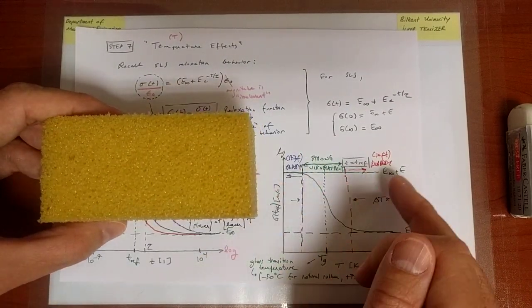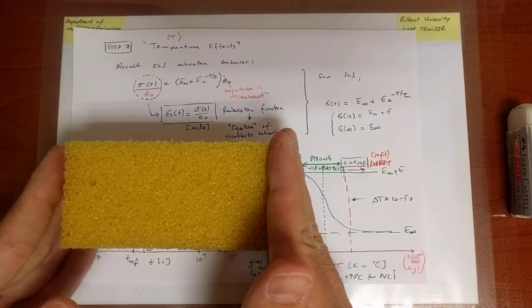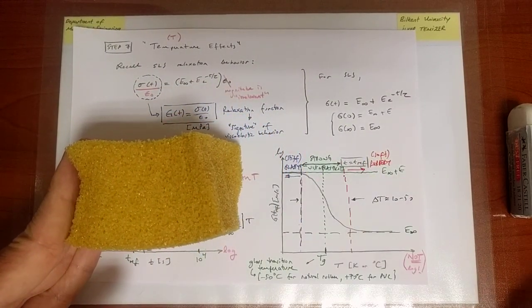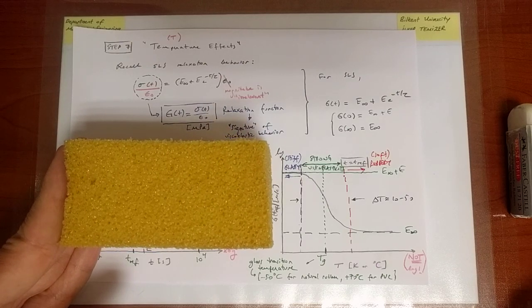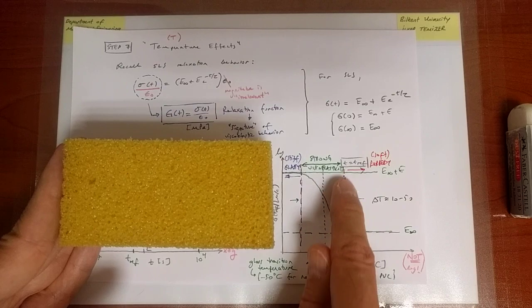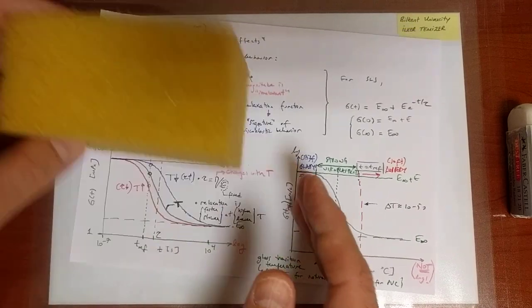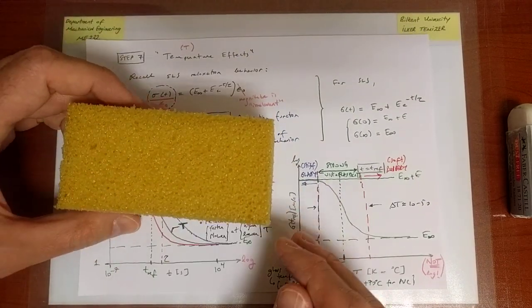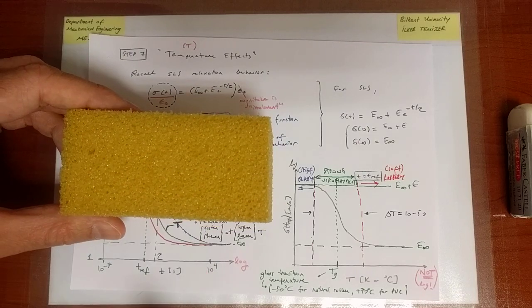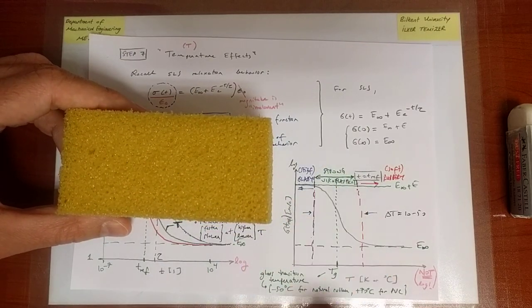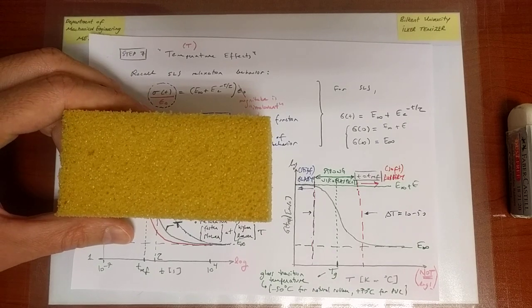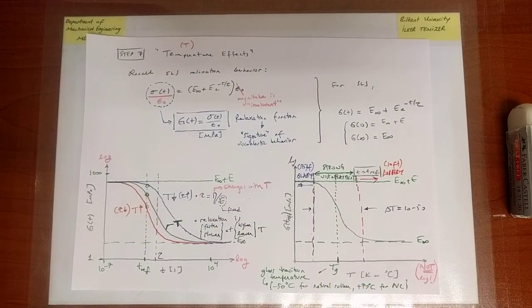Now, on the other hand, one example I gave you was sort of rubbery, the other one was glassy. If I take something like this, where does the glass transition temperature of this thing lie? Probably near room temperature, because I'm observing strongly viscoelastic material behavior, strong time-dependent effects, right? Time-dependent effects easily at room temperature, and hence this material is governed by this region, must have a glass transition temperature that is close to the room temperature. So that's how you can practically reflect all of those observations into some daily life experience.